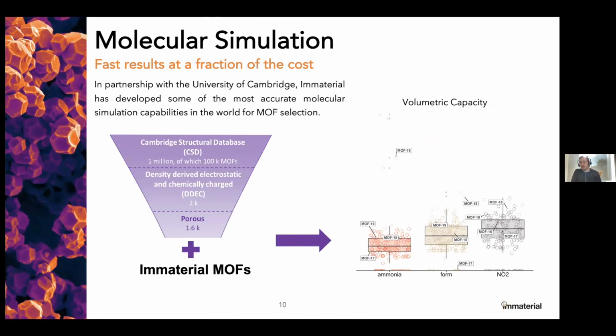Now, in parallel to this breakthrough testing, which we use to iterate on optimizing the materials, we also conducted molecular simulations in collaboration with the University of Cambridge. This is something that we've done quite regularly, and it works from the Cambridge Structural Database, where these 100,000 structures of MOFs I've mentioned a few times are all held, and then down selecting for hydrophobic MOFs. So we were keen for moisture in the air to not impact the performance of the structures that we were going to work with. So down selecting for hydrophobicity was certainly helpful in that. And then the further down selection in matching the porosity to the pollutants that we're interested in, making sure the pollutants can fit in the pore structures.